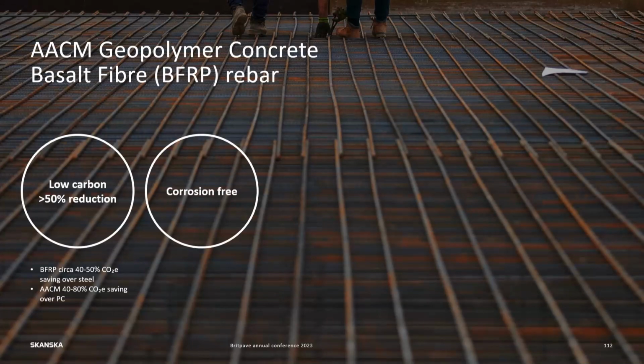Basalt fibre is also around 40 to 50% saving. But what are we comparing that against? Steel manufactured in what sort of way? Is that 100% recycled steel, electric arc furnace process? Well, obviously, if that was the case, the saving would be at the lower end of that spectrum. But nevertheless, it's a significant saving.